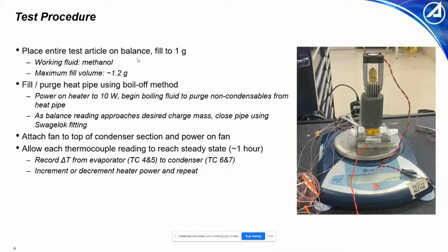Then, in order to create a hermetic seal, we use a fill, purge, boil off method. We powered the heater on to 10 watts and began boiling the fluid, with the goal of purging non-condensable air from within the heat pipe. As we're boiling and the balance reading approaches our desired charge mass, we close the pipe using the swage lock fitting and attach the fan to the top of the condenser section, then simply allow the thermocouples to reach steady state. In most of these tests, steady state was reached after approximately an hour.